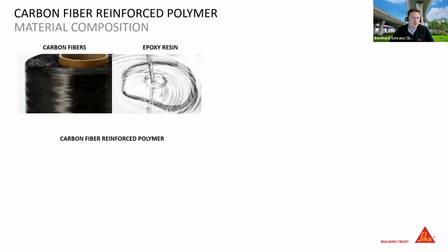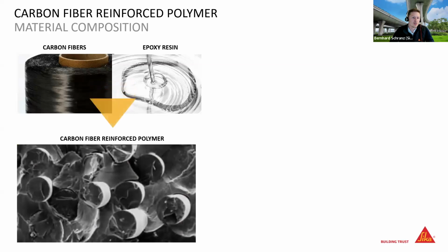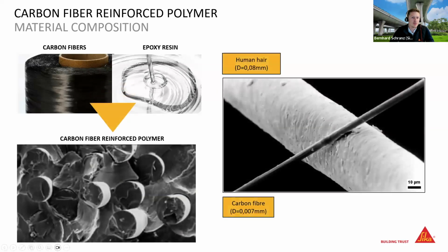We believe carbon fiber is a highly effective solution. So what it is, basically, is carbon fibers embedded in an epoxy matrix, usually, which gives you carbon fiber reinforced polymer, so CFRP. When you compare the carbon fibers to a hair, a carbon fiber is much smaller. So in each CFRP plate, you have thousands of those fibers.